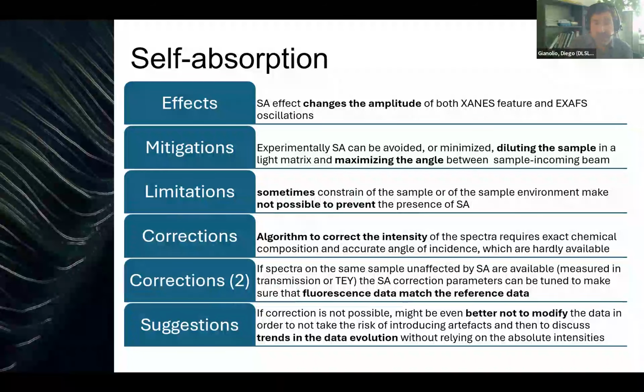But there are limitations. Sometimes the samples cannot be diluted, or the sample environment doesn't allow you to rotate it in grazing incidence. So sometimes it's just not possible to prevent the presence of self-absorption. And theory can help us in correcting the data. There are algorithms available to correct these changes in intensity in the spectra.